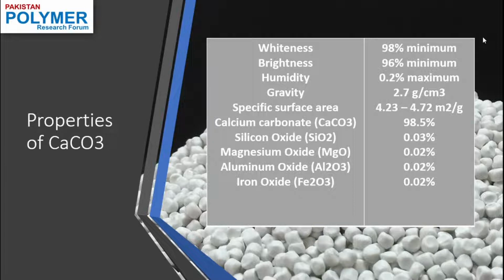There is a general rule that if you have a small size calcium carbonate, it will probably have a high oil absorption and you have to use more of the resin as compared to using a larger particle size of calcium carbonate. So for the choice of the resin for the formulation, you have to take into consideration not just the quality of your calcium carbonate but also its properties such as the particle size and the oil absorption. These properties are necessary because you're using it in a larger amount, like up to 80%, so it will surely have a very large impact on your end product and your processing.